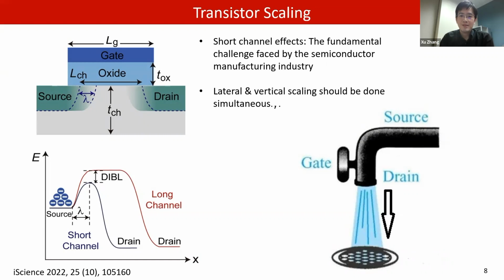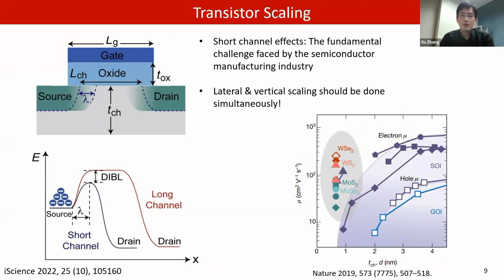Well, a rule of thumb is that the lateral and the vertical scaling of a transistor should be done simultaneously. When you make the transistor channel shorter, you have to make sure that the semiconductor channel and the dielectric layer also get thinner and thinner. Intuitively, that will allow the gate to physically get closer to the channel and maintain a tight electrostatic control. And that turns out very challenging to achieve, especially nowadays.